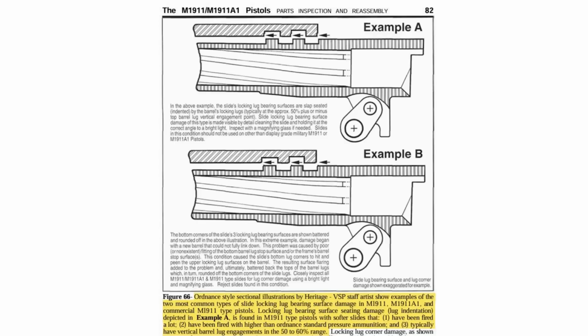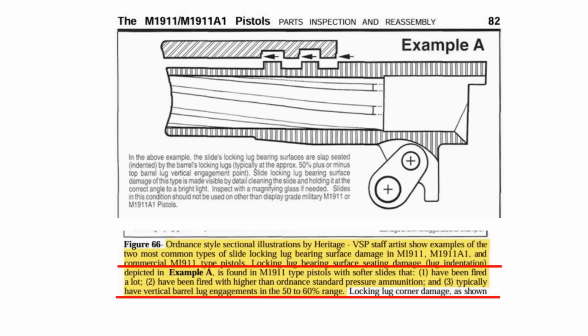In the M1911 Kuhnhausen manual, page 82, they claim lug damage generally occurs in pistols that have vertical lug engagement in the 50 to 60% range. But this often coincides with other issues like soft slide material, high round count, and the use of overpressure ammunition. So that 50 to 60% by itself may not cause issues.